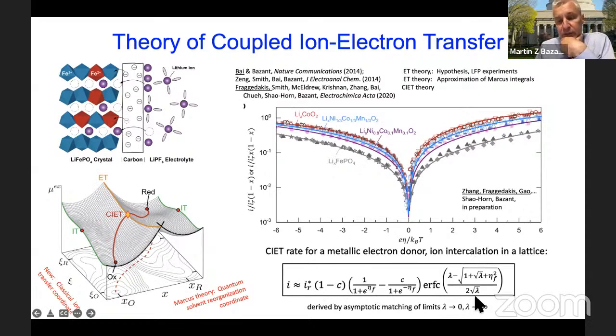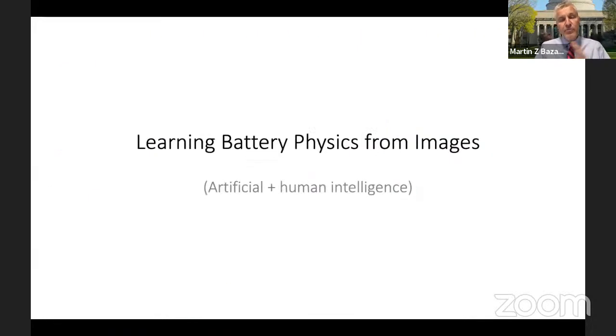So we have this theory, and it predicts a different dependence on overpotential and concentration than the Butler-Volmer equation, which everyone is using. But it's very difficult to tease this out of actual battery measurements because it's so complicated and you only get to measure an integrated quantity. And this is where images come in. In fact, I will argue to you that the kinds of measurements we've accomplished here by looking at images give you insights in the system that simply would not be possible any other way. If you can't look into the system and see the distribution of concentrations as the system is driven far from equilibrium, there's no way to learn or frankly even measure the kinetics of the reaction.